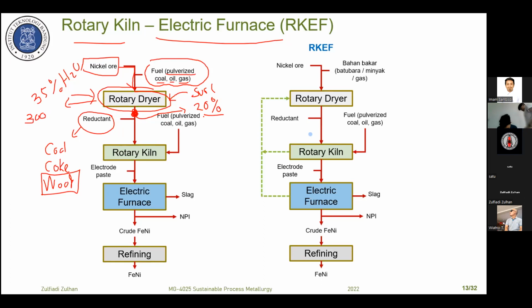And then the dry ore, which we also call conditioned ore, is mixed with reductant and charged into the rotary kiln. Similar to the rotary dryer, we can use pulverized coal, oil or gas as the energy source for the burner in the rotary kiln. The maximum gas temperature is around 1000 Celsius degrees, in some cases around 1100 or 1200. And here we get the product.